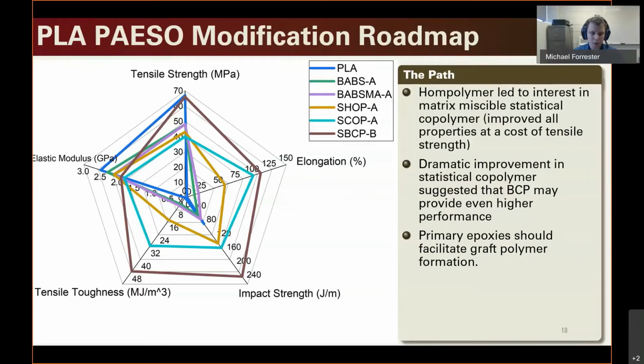So we wanted to go a little bit further because we hadn't quite met the ABS-like properties yet. And so one of the things that's pretty well known about PLA and polymers in general is that when you're trying to do modification using microphase separation methods, one of the things that really helps is if you improve your interfacial interaction. And so we got to thinking about matrix miscible blocks that can help to do that.